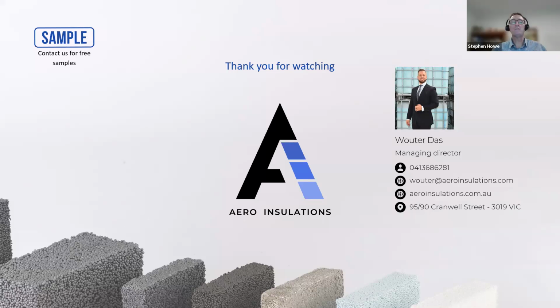Yep. So obviously you have various mix designs to suit different situations. It's not one mix design for all situations. No. We play around with the cement content, and if we really want to get to strong results, say for example, a hollow core block fill wall, like a besser block wall, and if you want to reach about 12 MPa, we need to add a bit of sand, maybe some fibers into the mix to get to that compressive strength result. With no additives except for EPS cement and our binder, we can get to about 6 MPa. And then after that, we have to add some stronger components, some additives and some sand, maybe some fibers.